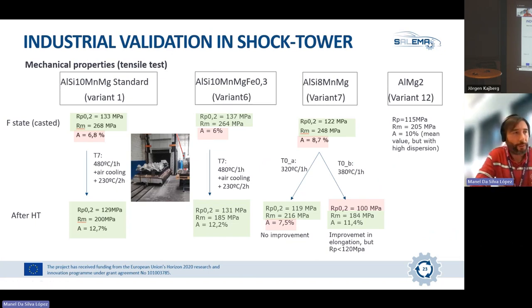And just to shortly show you the results we achieved. With variant 6, which is a variant produced with about 90% of end-of-life scrap, we were able to have mechanical properties close to the benchmark, the standard alloy. The elongation was reduced slightly, about 10%, but we also had a small increase in yield strength. And after the T7 heat treatment, we were meeting the requirements of the demonstrator: 120 megapascal for yield, 180 for ultimate tensile strength, and 10% of elongation.